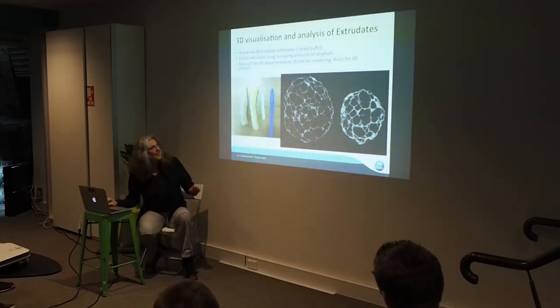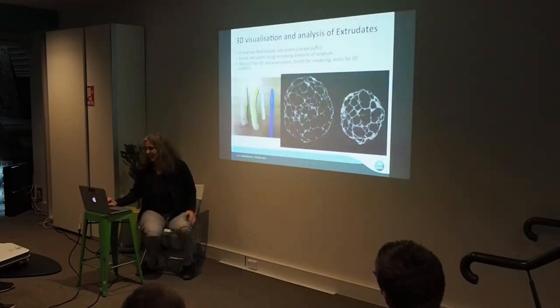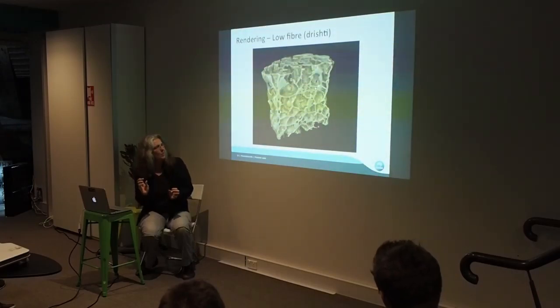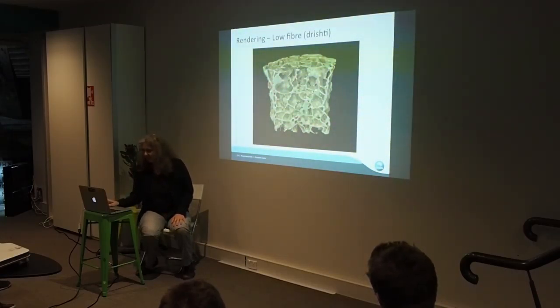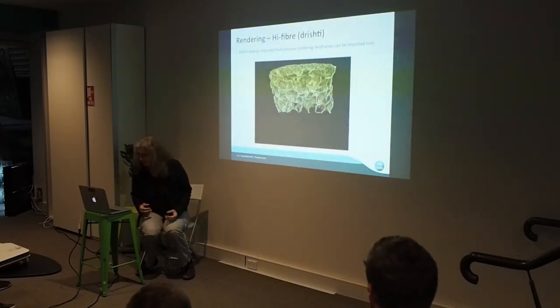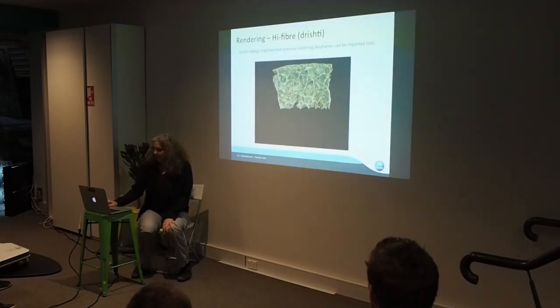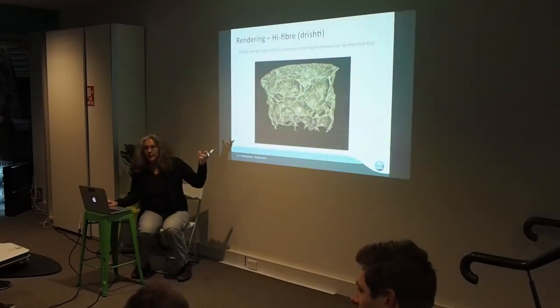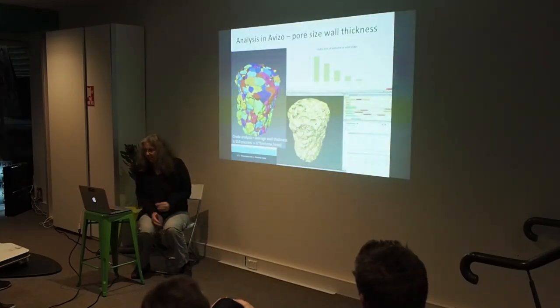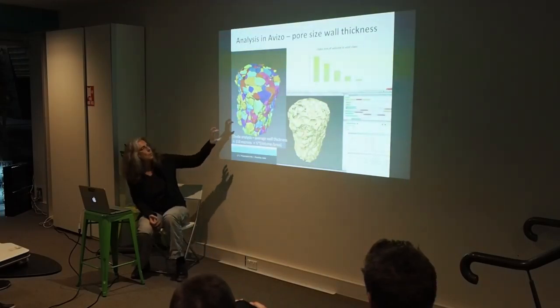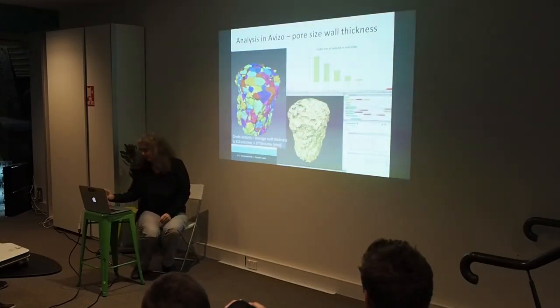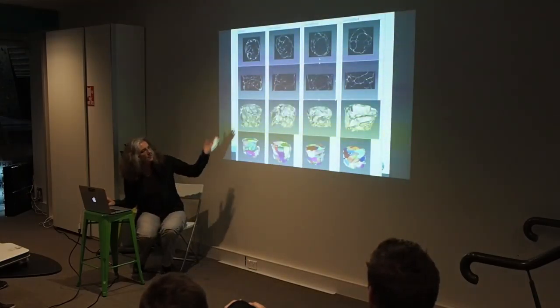They asked me to scan some of these for them. On the left are some examples, and on the right are some cross-sections. This is a rendering of the low-fibre one. Weirdly, the low-fibre one has thicker walls, which probably means it would be a bit hard to bite and not quite as nice. Whereas the high-fibre one is probably more puffed and lighter and probably better for you. This was done in Drishti, which is freeware and quite nice — from an art point of view I prefer Drishti. Our colleagues obviously want quantitative data, so they got me to measure all the pore sizes, bubble sizes and wall thicknesses. We can do a lot of comparisons.